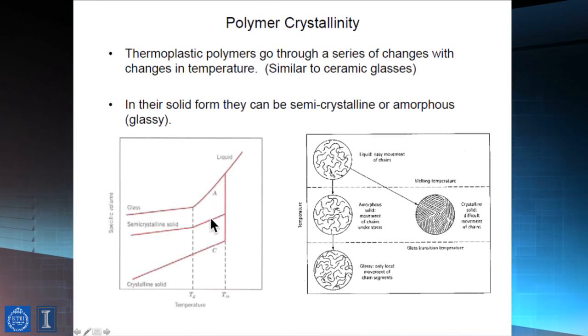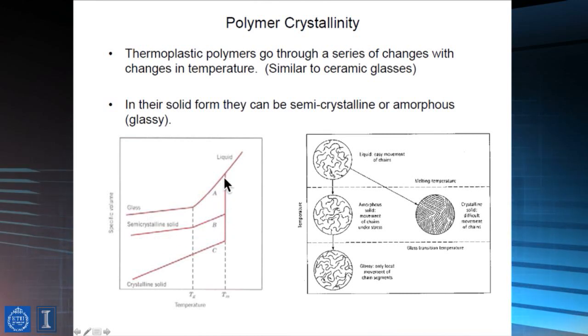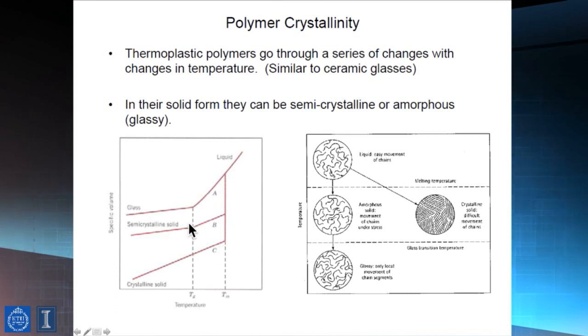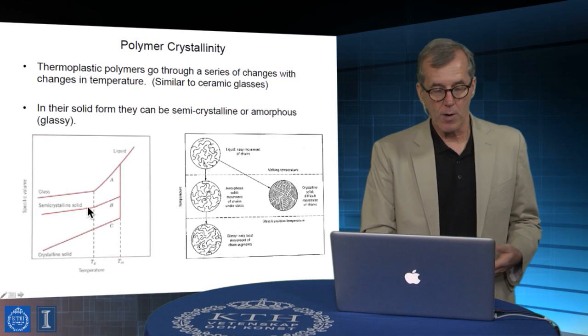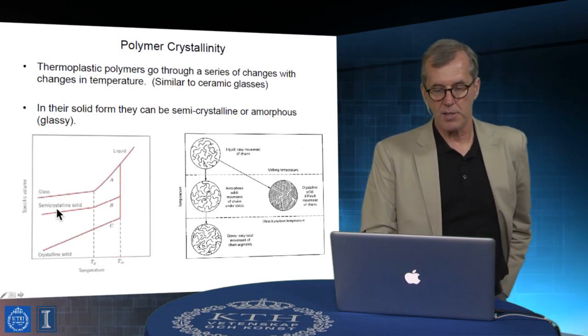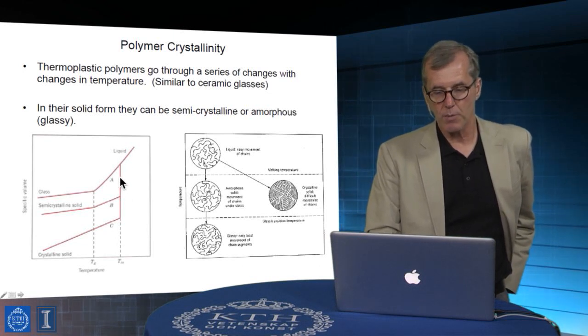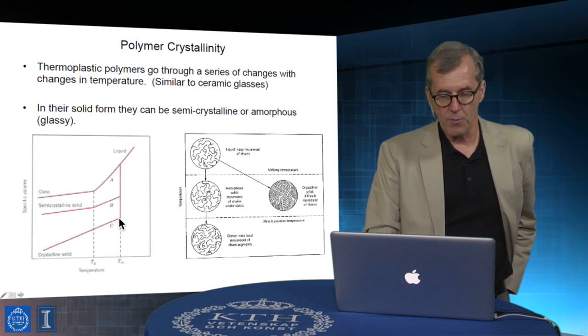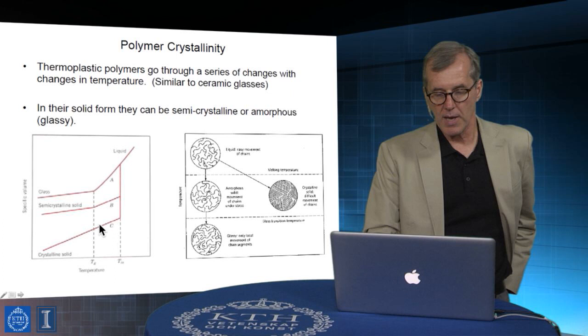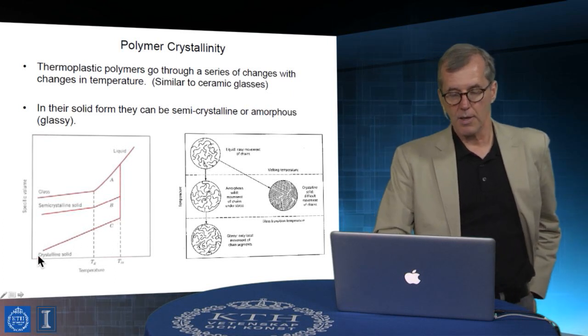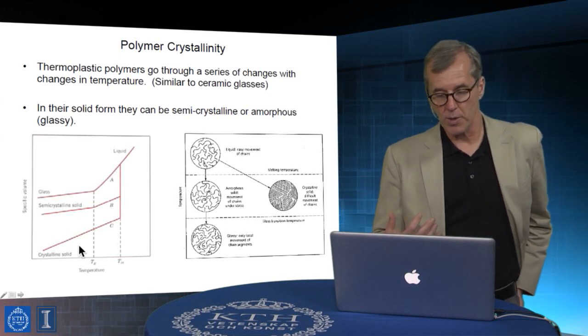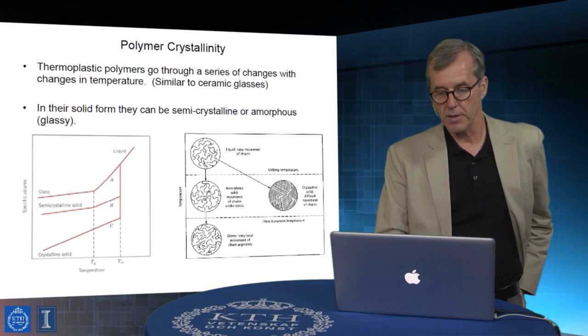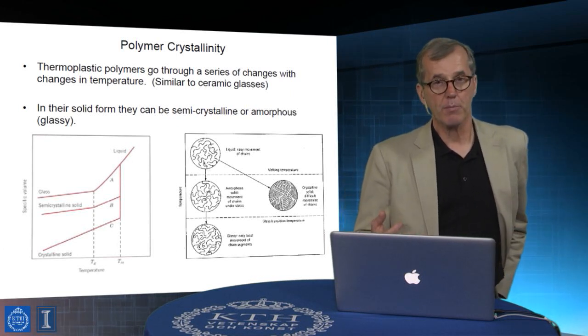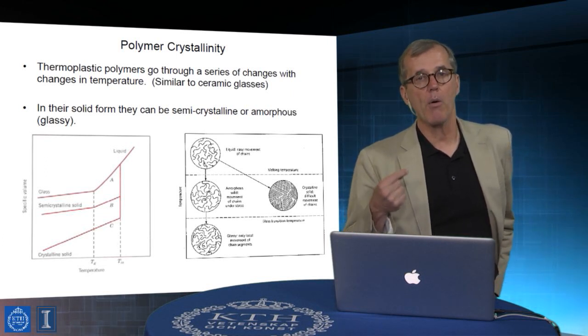And then we go along until basically the thing gets stuck again. And so what's basically happening in this area is that we've had some transition to crystalline form, but material that's been retained in an amorphous form actually then forms a glass component. So that's a more heterogeneous structure. And then in the case where a material is completely quenched and forms the crystalline phase, the behavior from there is also well behaved and as expected for a dense phase, just showing the normal change in density with a change in temperature. Okay, so thermal properties can be measured, and we'll see in subsequent lectures how that can in fact be done.